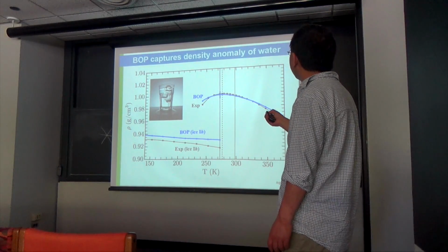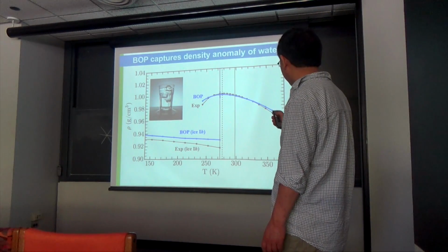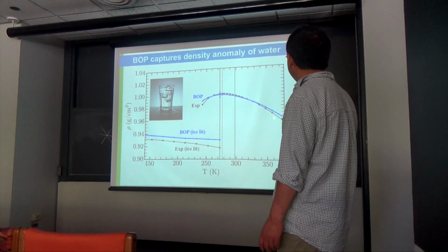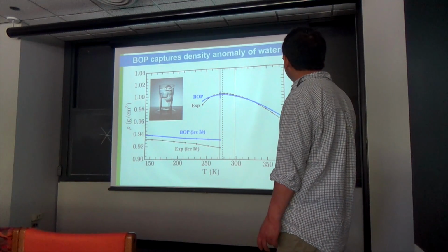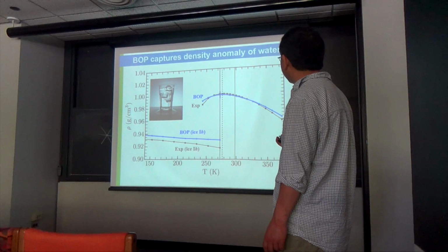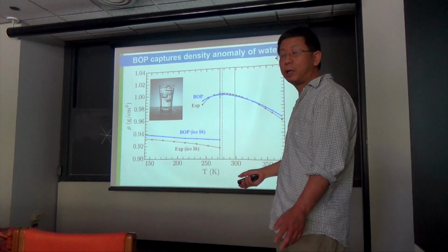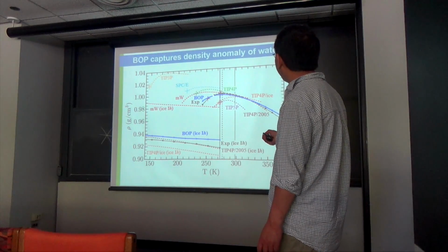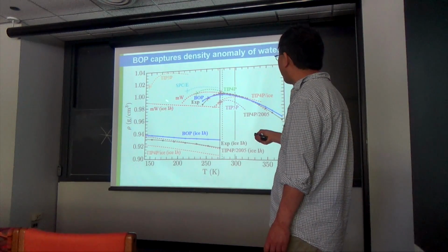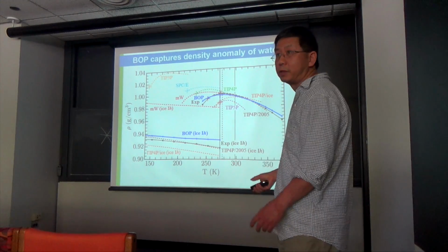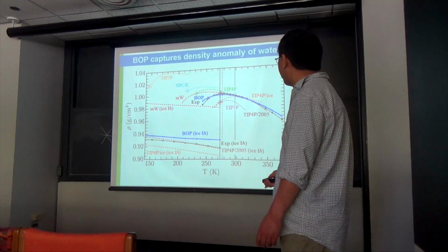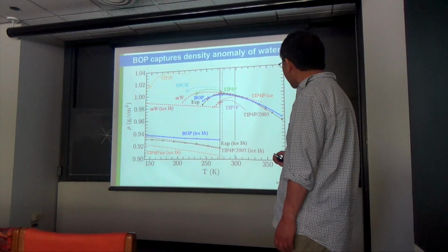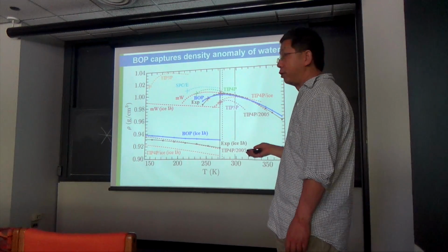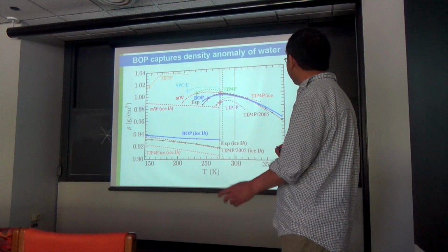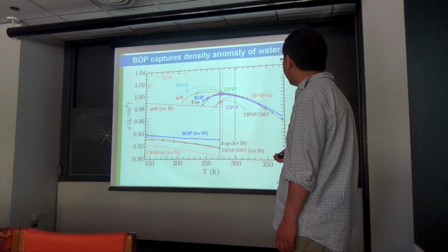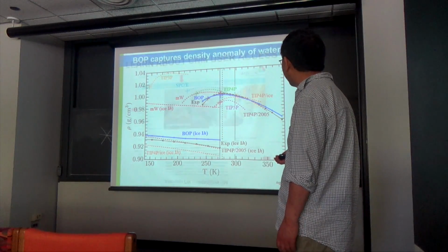So these are basically the density anomaly of water. Experimental data is plotted in black points, and the new simulation data is plotted in these blue curves. They match really, really well, compared with a lot of models with different kinds of approximation. And you can see this blue curve is much more accurate in reproducing water behavior. And this is still an ongoing effort in their lab. I think they have almost ready, or at least partially submitted, their manuscript already.